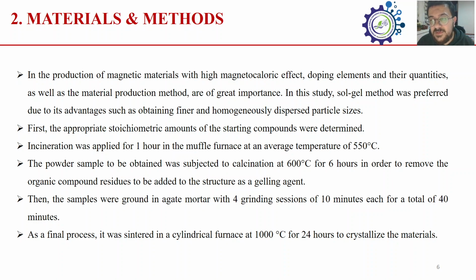In this study, the Sol-Gel method was preferred due to its advantages such as obtaining finer and homogeneously dispersed particle size. First, the appropriate stoichiometric amounts of the starting compounds were determined. Incineration was applied for 1 hour in the muffle furnace at an average temperature of 550 centigrade degrees. The powder sample obtained was subjected to calcination at 600 centigrade degrees for 6 hours in order to remove the compound residues added to the structure as gelling agents.